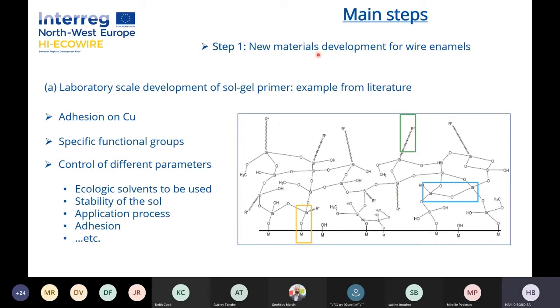For the first step, the material development of the new enamel wires, we have to develop a sol gel primer at laboratory scale and also for larger scale application. We have to choose the best chemistry to have good adhesion of the sol gel on the copper substrate. We also have to choose a specific chemistry with some functional groups to be compatible with the polymer that will be applied as the dielectric material on the sol gel coating after its application.